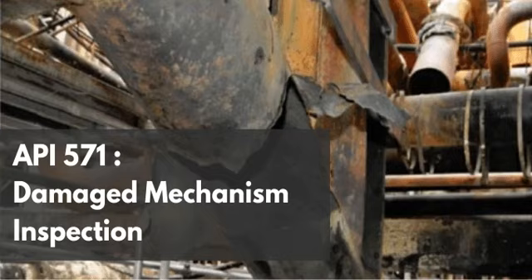Okay, so once you successfully identify the crack on the surface, without smearing it, the immediate operational question is sizing. How deep does the spider web go? Can the unit run until the next scheduled turnaround, or do we need an emergency shutdown? Right, the fitness for service evaluation. For depth sizing, the guidelines point to volumetric NDE methods, specifically angle beam ultrasonic techniques, shear wave ultrasonic testing, SWUT, and phased array ultrasonic testing, PAUT.